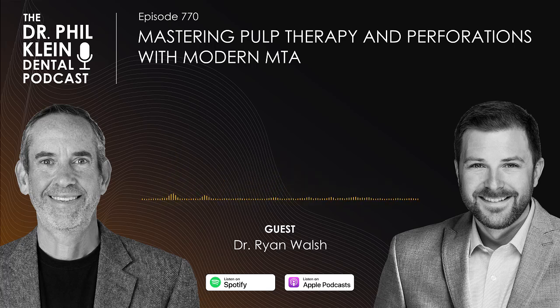You're stimulating hydroxyapatite formation. Again, that constant release of calcium reacting with the phosphate in the body. Calcium and phosphate, you're producing the precursors for hydroxyapatite. And from there, you're recruiting those cells to form a dentin bridge or osseous tissue. It's really just the same type of reaction, just applied at different levels inside the tooth.